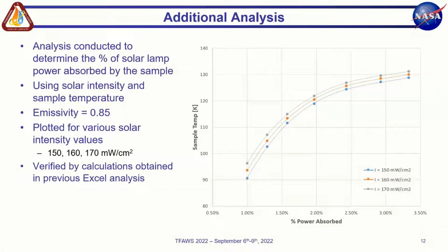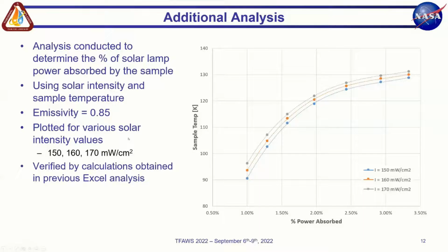And lastly, the additional analysis that I wanted to discuss was conducted to determine the percent of the solar lamp power that was absorbed by the sample. This was done using different solar intensity measurements, and plotting for different solar intensity values, 150, 160, 170. So the model setup here involved the same conditions as you saw for the light on case.